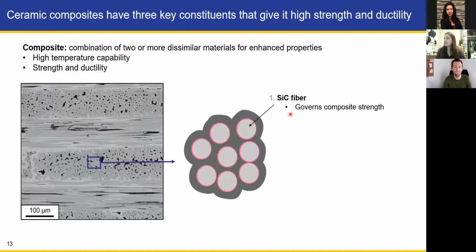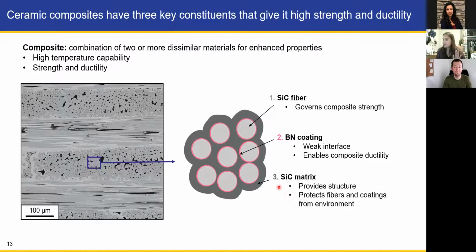First is the silicon carbide fiber. These fibers are very high strength, and they govern the entire composite strength. So that's what gives it strength here. The second is a boron nitride coating that surrounds the fibers. It's designed to be a weak interface so that when cracks come in, it deflects around the fibers rather than cracking straight through the fibers, keeps them intact, and it enables the ductility of the composite. And finally, our silicon carbide matrix provides structure, protects fibers and coatings from the environment, which we'll talk about soon.